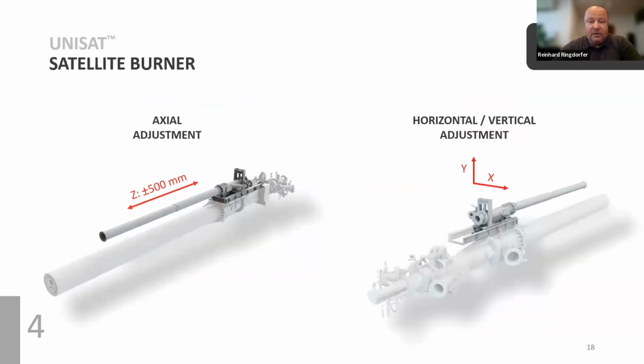So as I mentioned before, usually the satellite burner is located a certain distance behind the burner tip. Here you can see the execution where the satellite burner is directly on top of the main burner. It's actually located on a small burner trolley, which gives you the possibility of adjustment plus minus 500 millimeters in axial direction. And if it's located on the burner itself, you also have the possibility of a vertical adjustment of the tip of the satellite burner. Horizontal adjustment will also be included if the satellite burner is located beside or above the main burner, so if it's not sitting directly at the main burner.